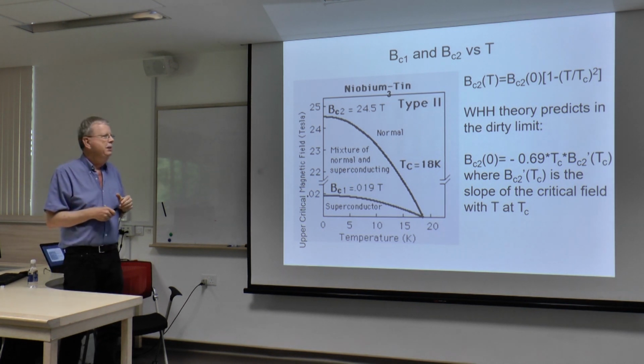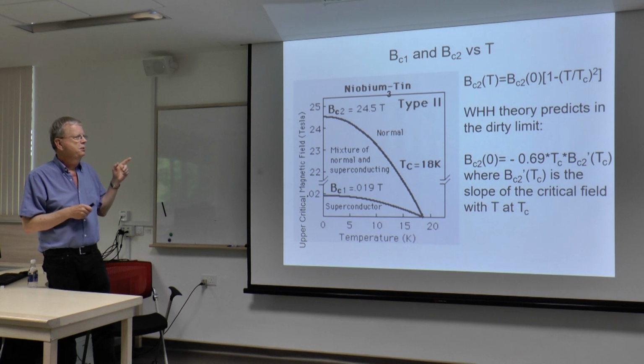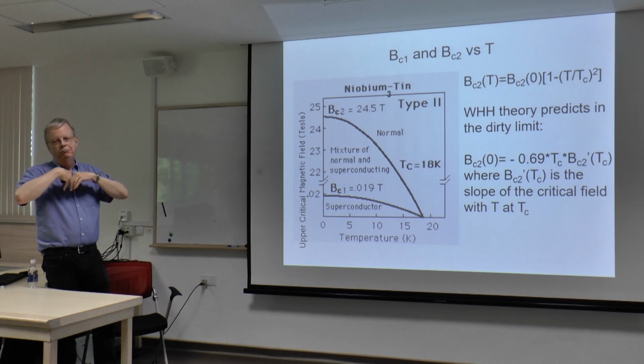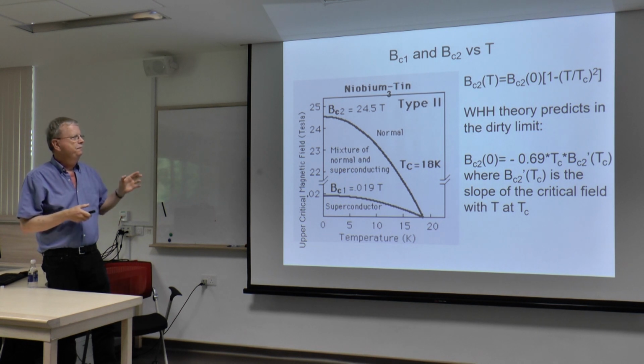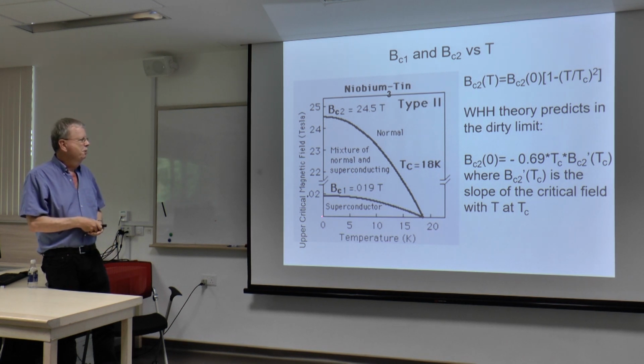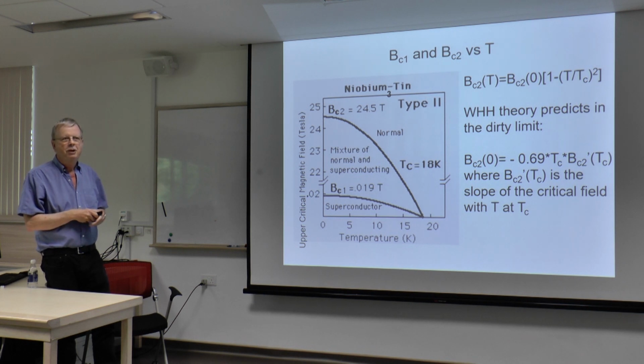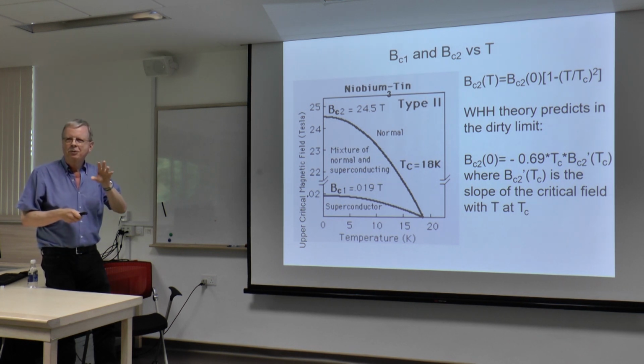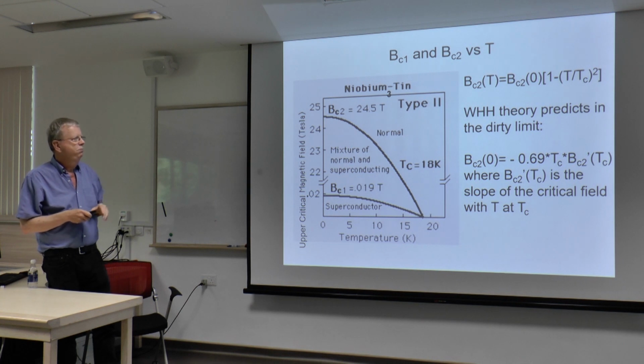So actually the inductance of our 16 Tesla magnet is 17 henries. So there's a whole lot of kilojoules in there. And when it quenches, it's an exciting event. I mean, all the helium comes out, just this big gas front. So you want to stay a little bit away from the theoretical upper. And the other thing is, I might point out, no one runs their superconductor at T equals 0. We haven't quite gotten there yet. Even in the millikelvin laboratory at Gainesville, still 1.9 Kelvin maybe.